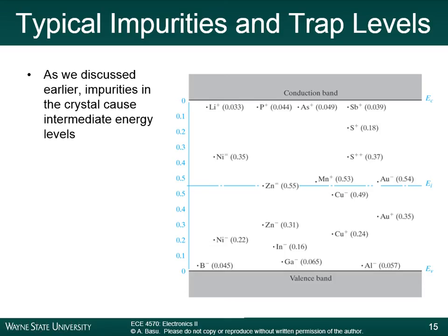So you have to have ultra pure water when you're dealing with semiconductor processes, or you will inadvertently put trap levels into your silicon, and you'll end up with these types of processes happening. Now, sometimes you intentionally want to put those impurities in there, as was the case with column 5 doping and column 3 doping. In some cases, you even want to get energy states near the intrinsic level. Sometimes you'll intentionally dope, and in other cases, when you don't want to dope, you have to make sure that you use ultra-pure manufacturing processes so you don't create these trap levels inadvertently.